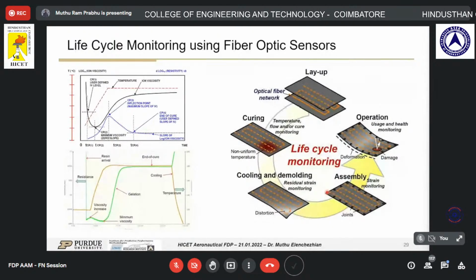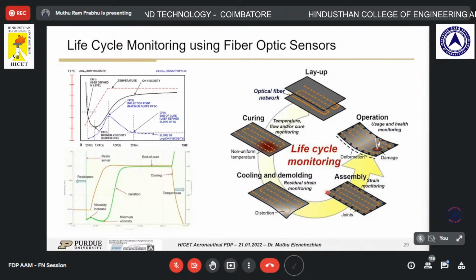Another advantage of using fiber optic sensors is that they can be placed completely during the manufacturing. That is, during layup, you can actually place the optical fibers into the entire composite structure by itself. And the strength of the composite hasn't been found to vary a lot based on this. After this, during curing, you can also monitor, based on temperature and flow, how good the composite curing is. And in operation, you will be continuously monitoring the real-time health and strength.